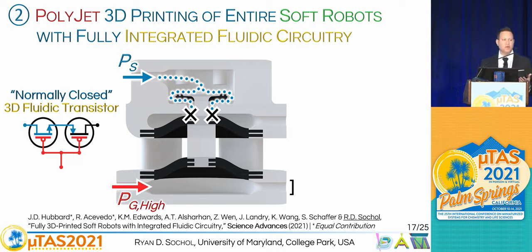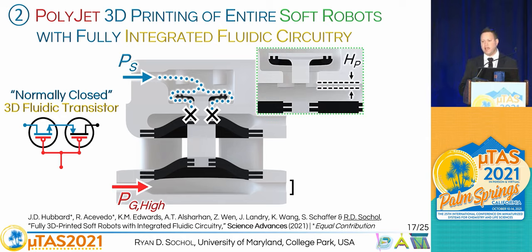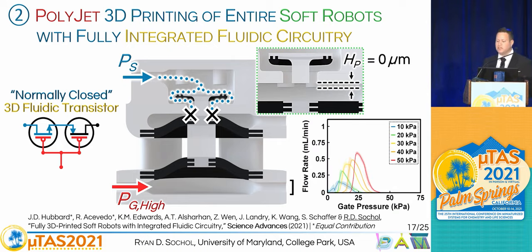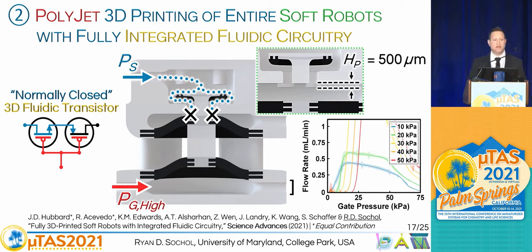And you can actually tune this behavior by changing the height of the micropost located beneath that orifice. If you don't include any micropost, if the height is zero, it's going to look something like this, where as you increase that gate pressure, you see flow come in and then flow drops out. But if you increase the height, it ends up limiting that reclosing function. So as you increase the gate pressure, it opens and then it stays open for quite a bit.